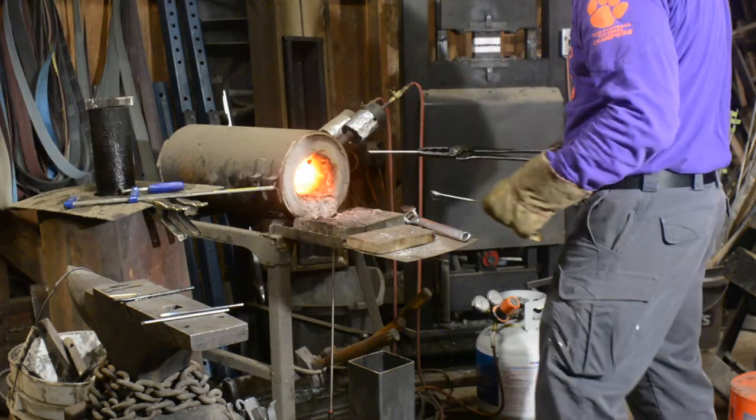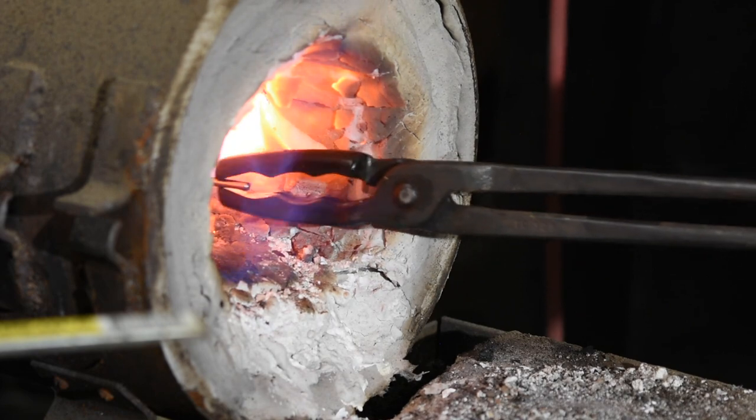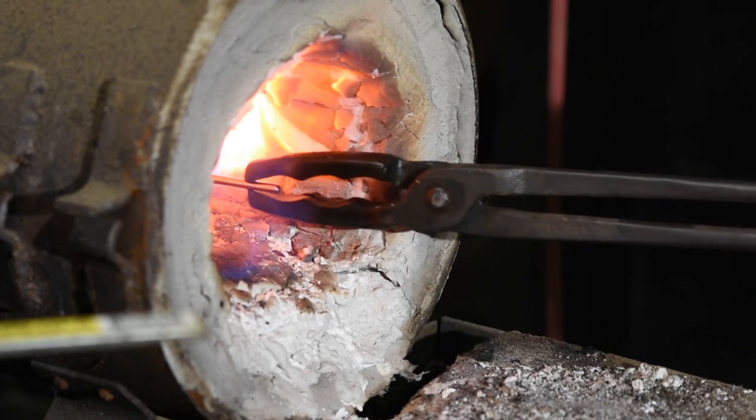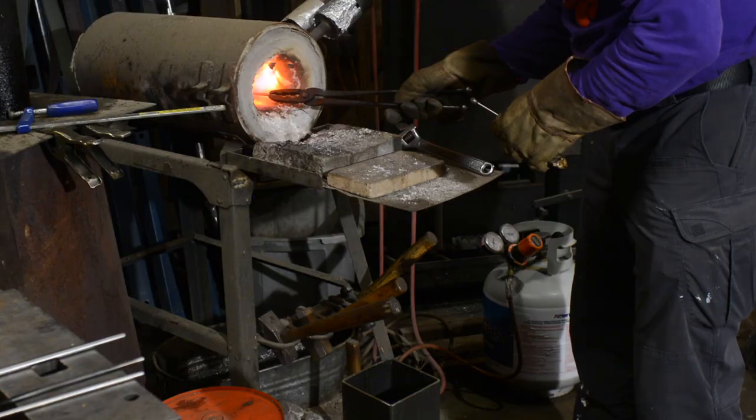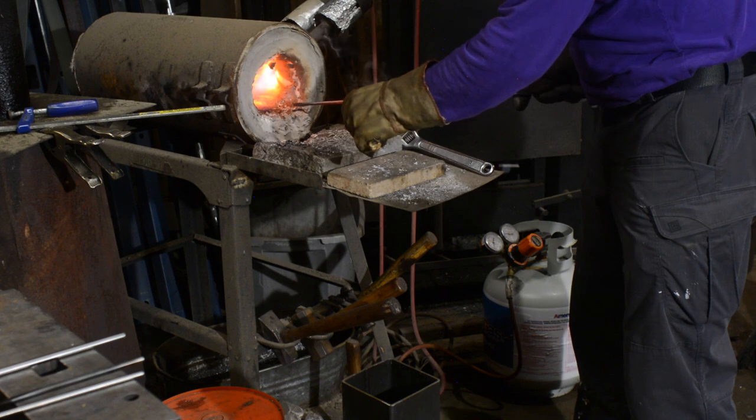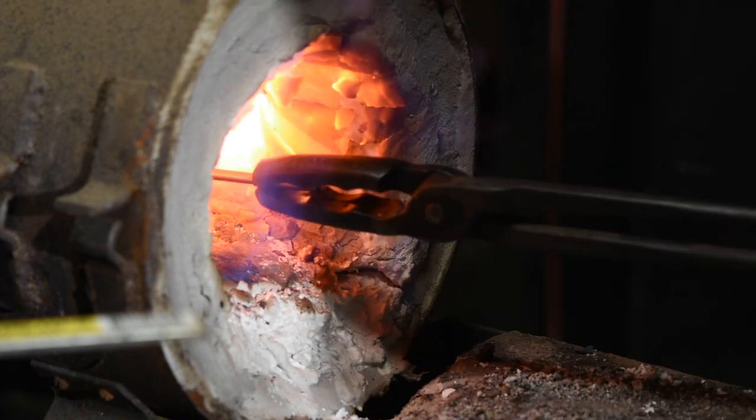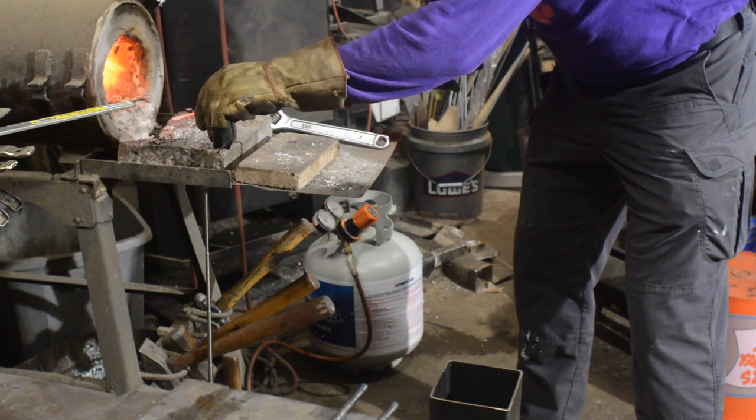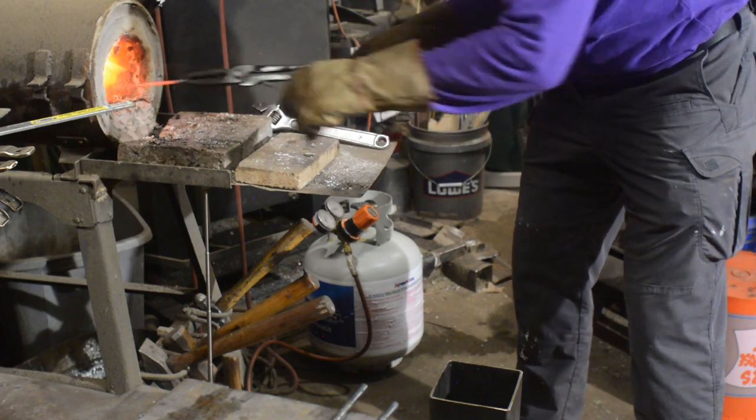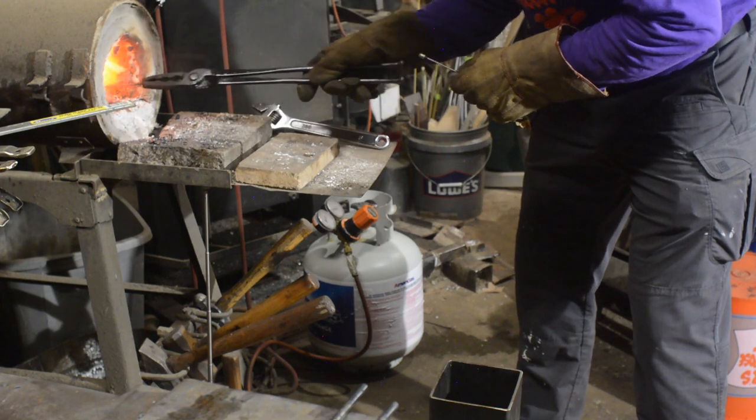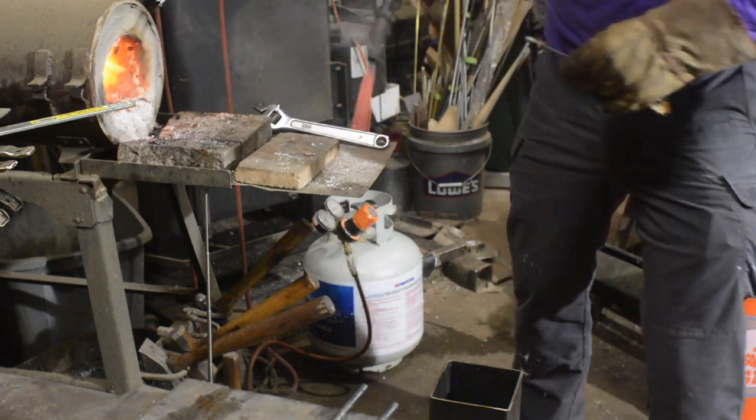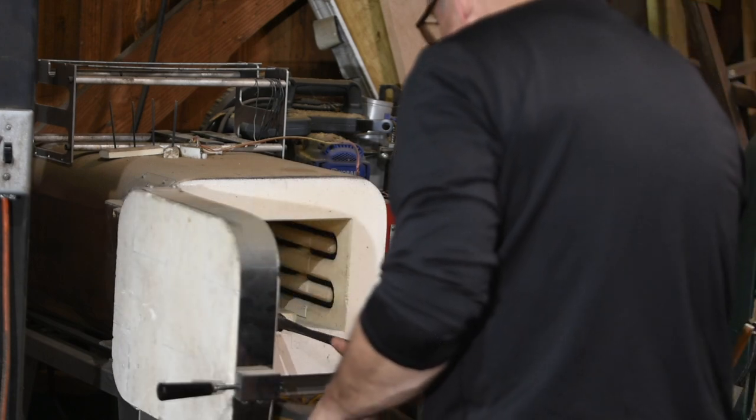Once the milling is complete, I'll heat treat them as I did in the other videos. Now just in case you're jumping in here and you haven't watched those previous videos and you think heat treat's something you can skip over, it is not. Heat treating is the single most important step in making virtually all tools. Basically what we're doing is taking steel that's in a soft state right now and hardening it to the level of hardness that it needs to have so that it won't strip out when you're turning screws with it. I heat the tools to 1500 Fahrenheit, quench them in oil, then temper them at 600 Fahrenheit to soften them up a little bit and make them more resilient.